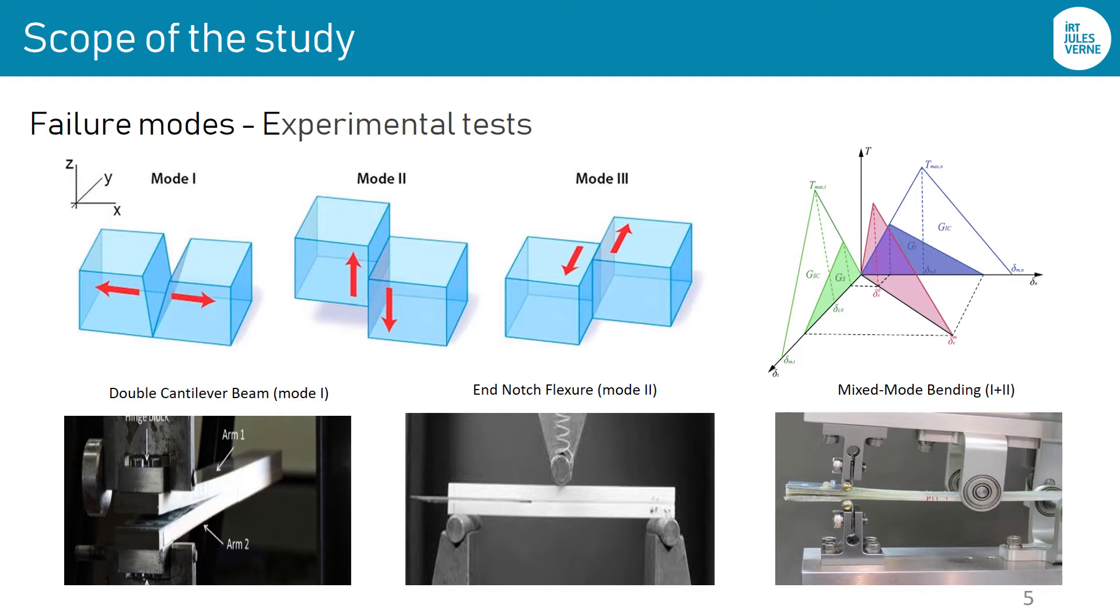Let's talk about fracture modes. These modes belong to the basics of fracture mechanics. The mode is defined by the loading and crack propagation direction. In the figure at the right, an illustration of a cohesive zone model able to describe mode 1, 2, and mixed mode. We can conclude that mode 1 results from normal solicitation, mode 2 is shear dominated, and the mixed mode results from the presence of both mode 1 and 2.